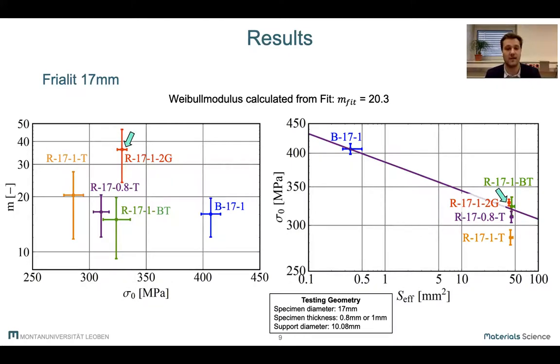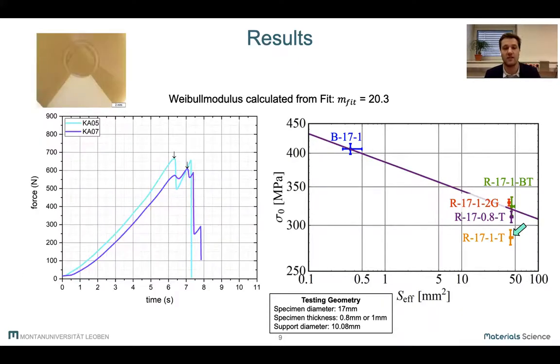And then there's this specific data set. It was not included in the linear fit, since the Teflon tape started to rupture just before failure, which resulted in two peaks close to the maximum load and unknown friction conditions at failure. The samples looked something like this after testing, which is why we would not recommend using the specific tape for high loads.